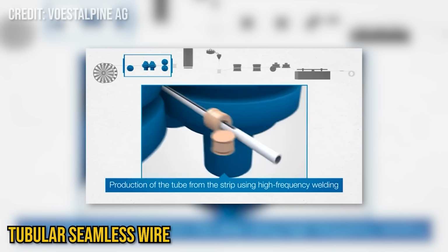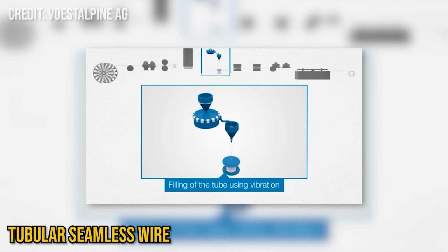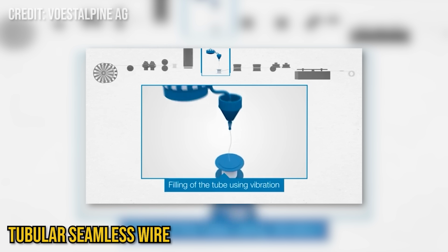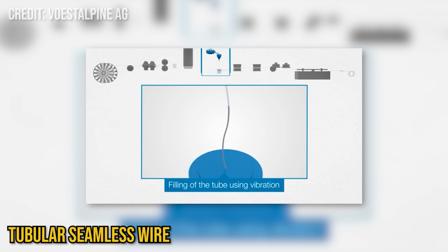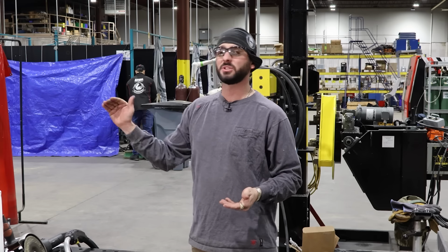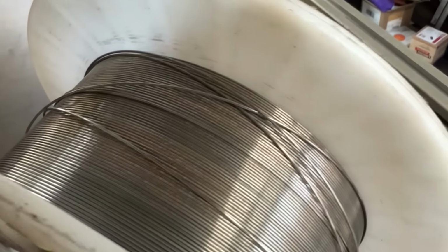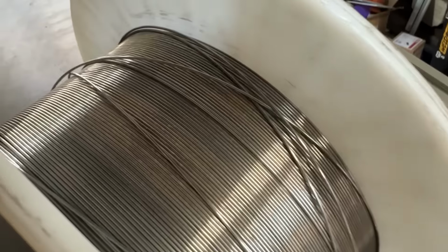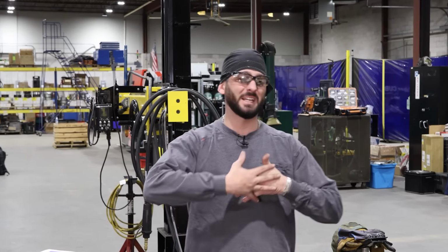Whereas your seamless cored wire is going to be manufactured a little bit differently. They'll get that wire out with that empty core, and they'll use vibration in order to get all those bits in there. Honestly, the seamless wire is very nice because it's pretty much 100% moisture proof. Whereas your seamed wire, if you leave it out in the open, it's going to be susceptible to moisture. Not only that, but the seam on that seamed wire can bust, and all those good alloying elements can come out of that wire, and now you've got just some bad wire.